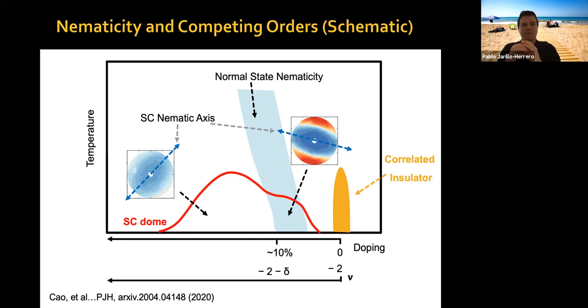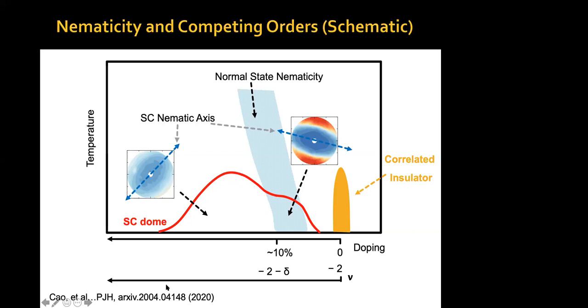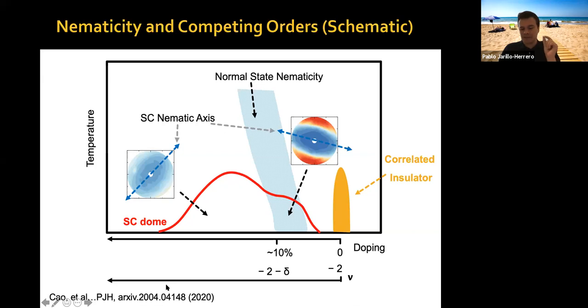Of course, if you have very strong strain and an S wave order parameter, you could have anisotropies in your superconducting state. But that would be a trivial way of getting nematicity. It's just imposed structurally by the external strain. But if you have something where, for example, your nematic axis rotates, that's highly unlikely to be due to an external strain or something like that. Then it indicates that it might be one of those superconducting order parameters. You can find a discussion about specifically which order parameters could be more likely. But again, it's just a suggestion.